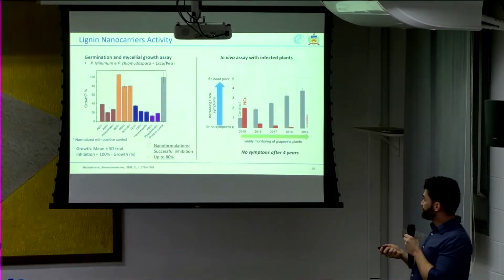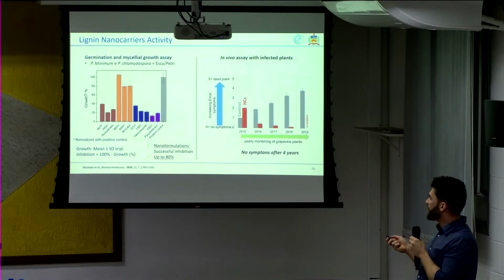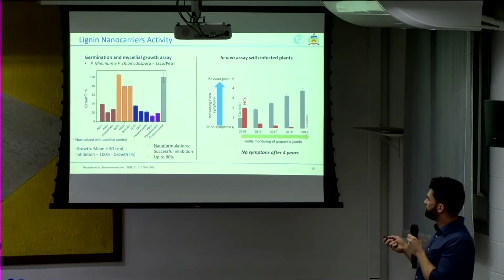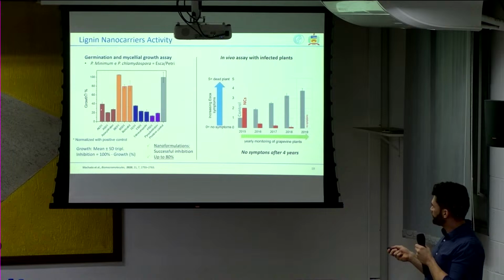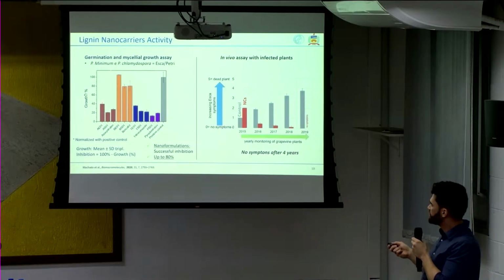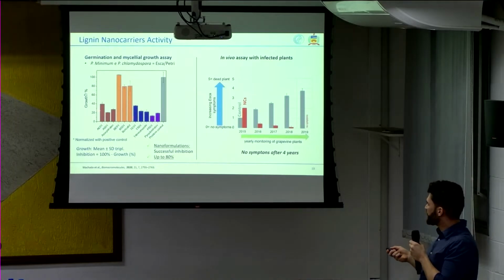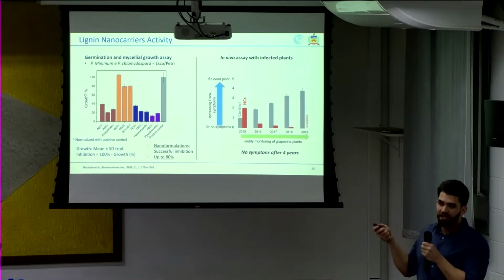After we got the carriers, we tested their activity. For lignin nanocarriers, we targeted Petri disease, and we did an assay with the spores of the fungi. I call it germination and mycelial growth assay. So the nanocarriers were always tested against the free fungicide, and the nanoformulations were up to 80% efficient. So they inhibited up to 80% of the germination and growth. Here, the free fungicides have a better activity because they are free. They don't need to be released in the medium.